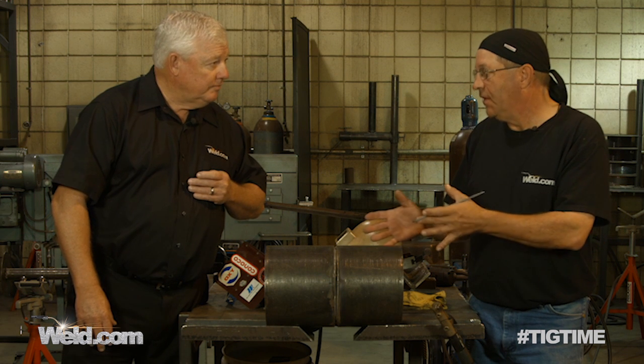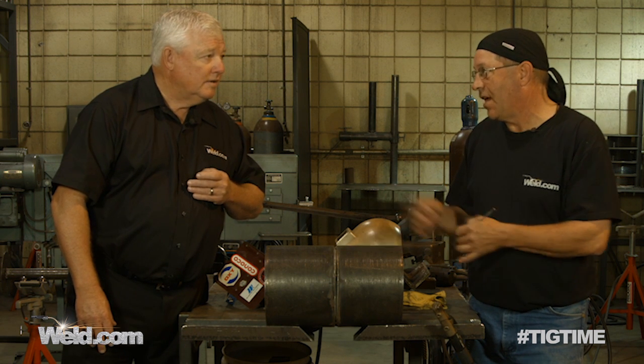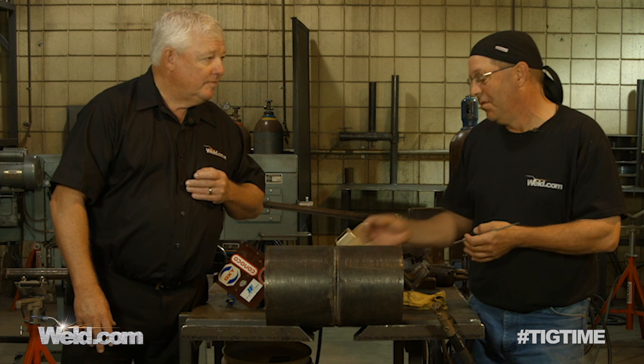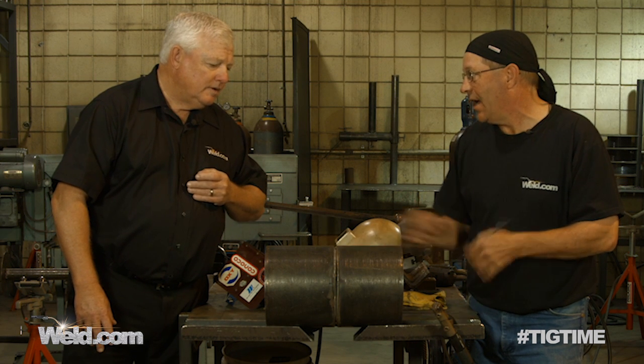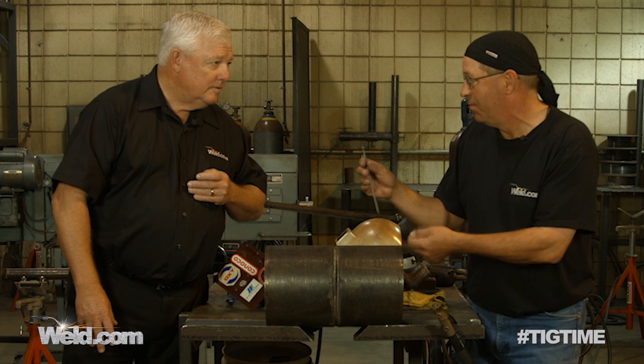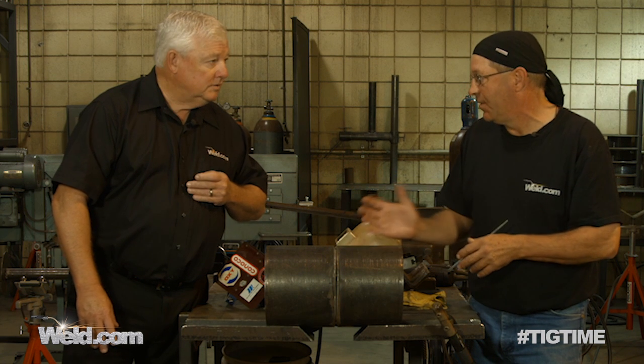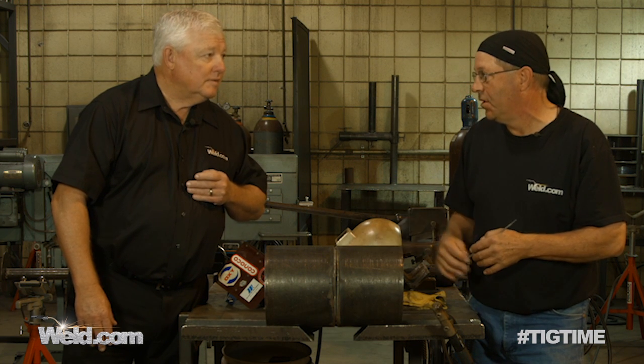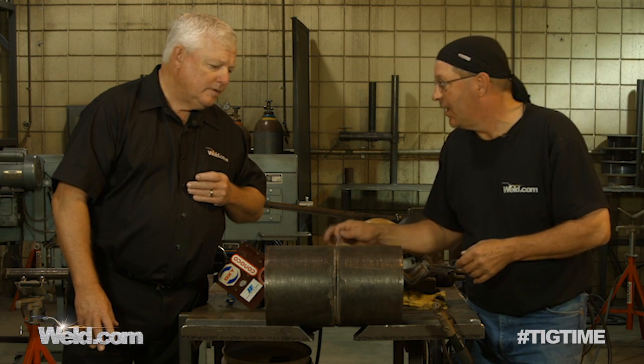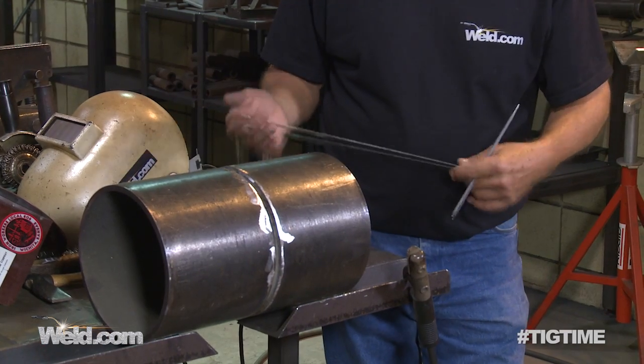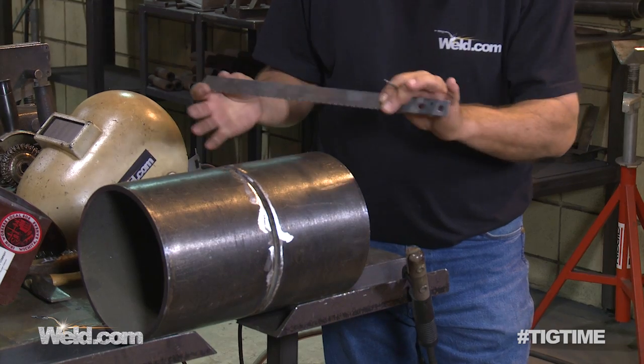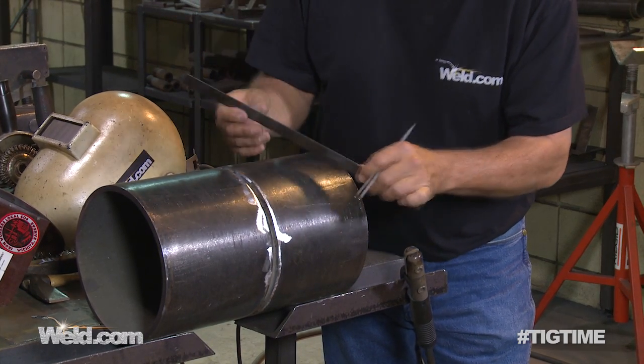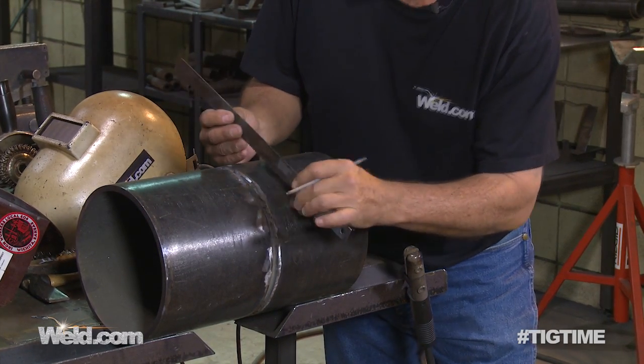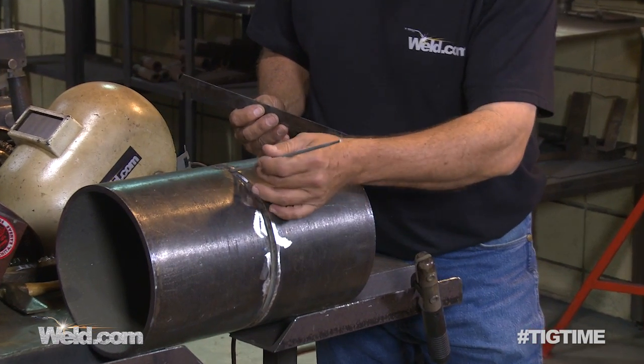The times that we've done these other sessions, we've done the gas tungsten or the TIG route, and we had a real big wide gap so that we could fit our filler wire to the inside of the pipe to get our fusion and our root reinforcement. You'll notice this barely has any gap in it. I like to fit my pipe when I'm doing the stick welding with like a saw blade, 3/32 or less, because this has such a violent digging type of arc.